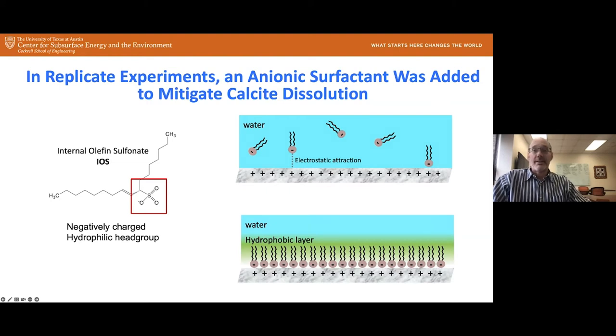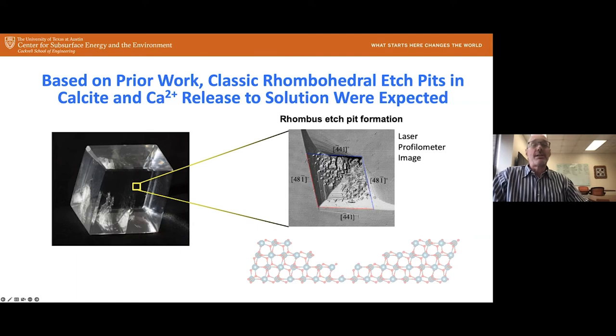So how does that IOS affect this? When we think about calcite dissolution, we think about what happens at the microscopic scale. In calcite dissolution, you start to get etch pits, which have a classic rhombohedral shape. This shape is comprised of a pit that has acute edges, or sharp angles, on one side, and on the other side, where the blue is, obtuse angles. Also, at the intersections, it has kinks: an obtuse-obtuse kink, obtuse-acute kink, acute-acute kink, and obtuse-acute kink. And then finally, it has steps out here on the flat. Usually dissolution occurs at the defects, so where we have these pits, edges, and kinks, that's where we start getting dissolution of the calcite.